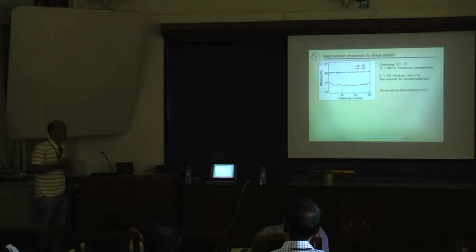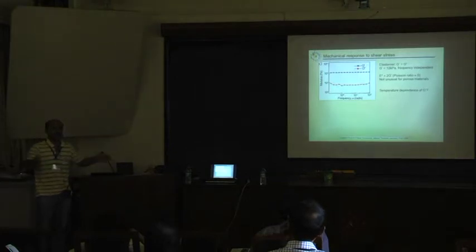We can take these materials and gently shear them at very low amplitudes of shear, and you get a G prime as you would expect for a network material, which is essentially frequency independent. It has a shear modulus of about 12 kilopascals, which is half of what we saw previously. It was 24 kilopascals. So the shear modulus is about half of the Young's modulus, and that suggests that the Poisson ratio is 0, which means that if you take this material and you squish it down, it essentially doesn't become fatter.